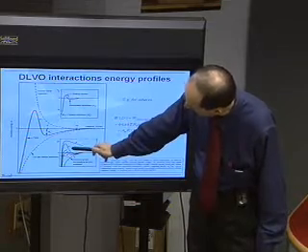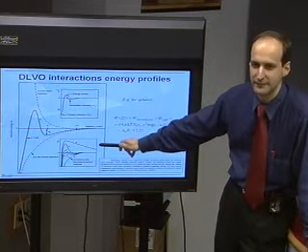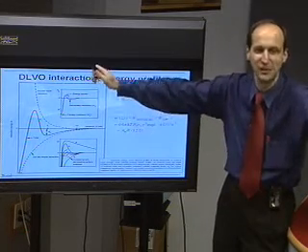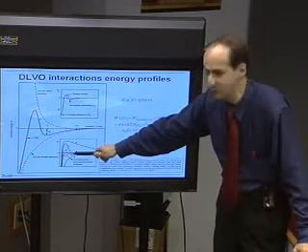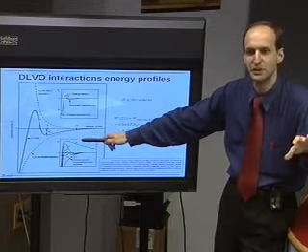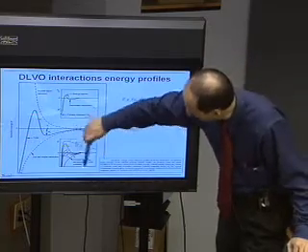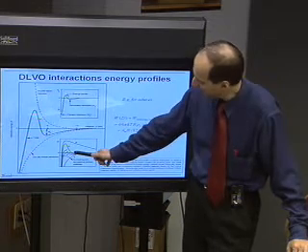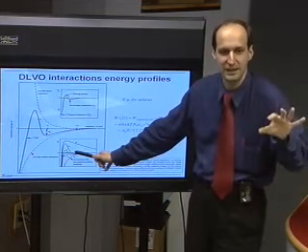So then, these are the different cases of what happens when you control the electrostatics by adding electrolyte. Without electrolyte, you have very strong, very long-range repulsion. And this is the reason why when we deionize latex, it stays a long, long distance away from each other. When you just add a little bit of electrolyte, which typically happens in room conditions by CO2 dissolution, you are going to have, this is the typical case which you have in practice, like curve B here. So the two particles can come relatively close to each other, but they are separated by electrostatics.